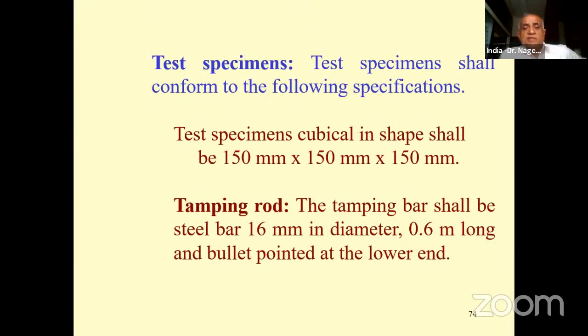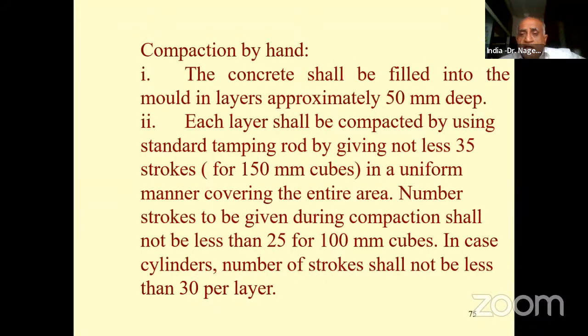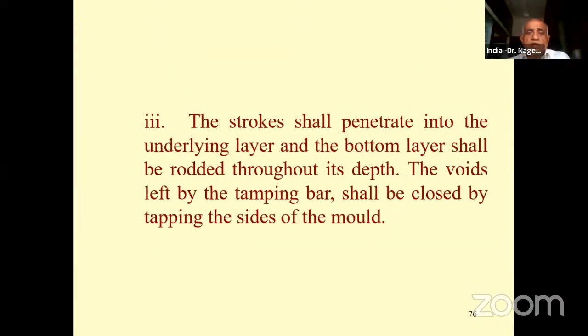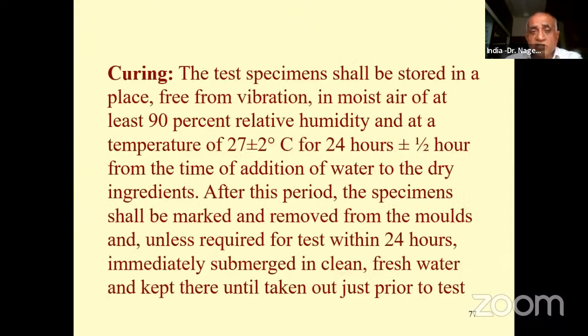Now, how is it done? We normally use 150 by 150 by 150 mm cubes. A tamping rod is used, and it is filled in three equal layers by giving 35 strokes to each layer. After giving 35 strokes to each layer, the concrete cube can be kept like that for some time and then finished. The strokes shall penetrate into the underlying layer. Okay, this is how the cube is cast.